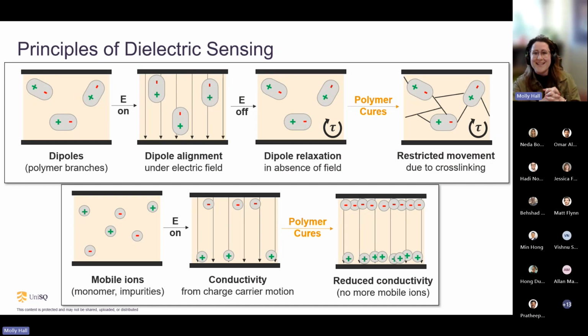But how does dielectric sensing actually work? In your thermoset, I'll take the fibers out for now. The fibers don't change through the cure. What happens during curing is your polymer is changing, and that's what we want to capture. So within your polymer, you have dipoles, which are commonly polymer branches or subgroups that are off of your polymer, and you have ions that are kind of floating around. These are commonly either impurities or unreacted monomers.